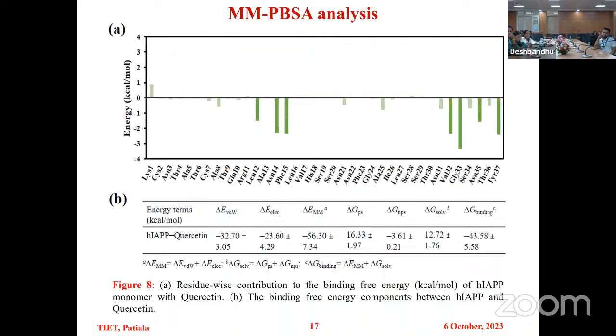Next, we performed the MMPBSA analysis residue-wise, and this analysis shows which residue of HIAPP is interacting with our quercetin. Residues arginine 11, leucine 12, glycine 33, asparagine 35, and tyrosine 37 showed significant contribution. And the binding free energy was also found to be really good, minus 43.58 kilocalories per mole.